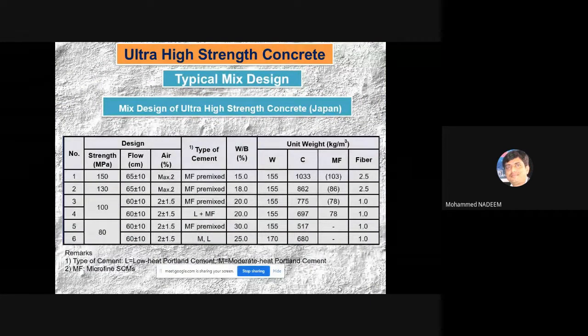So this is a typical mix design of a concrete if you are making an ultra high strength concrete of 150 MPa, which is practically not possible otherwise. Normally people keep flowability at self-compacting concrete level, because concrete has to be pumped to a height of, say, 100 story or 80 story. You can't think of manual transportation. You need to pump it, and given the congestion of reinforcement, one has to have a very flowable concrete. So even high strength concrete must be flowable. And you have to use microfine material along with cement and SCMs in the form of fly ash or GGBS, which we'll see.